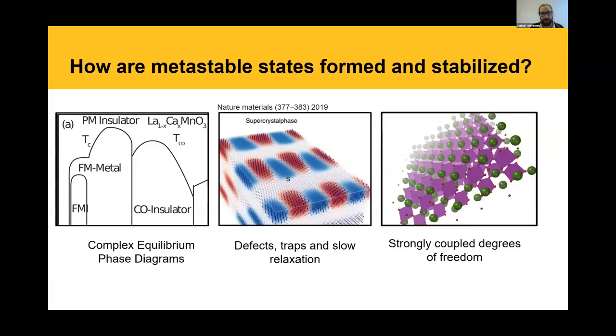Typically in ultrafast science, we think of collective excitations. We think of things like A1g modes, where the entire system is doing the same thing at the same time. But that's not necessarily true at long times. We've seen in systems from tantalum disulfide to the manganites that things like domain walls are really important for stabilizing these new phases. And finally, we need strongly coupled degrees of freedom, which feeds back into the complex equilibrium phase diagrams. In the manganites, you have strongly coupled lattice, charge, and magnetic order, which I'm going to talk about in some detail today. In other systems, you can have, for example, strongly coupled lattice and charge order in the TMDs. This is important because you need an activation barrier between your hidden metastable photoinduced state and the ground state, and that's what the strong coupling gives you.